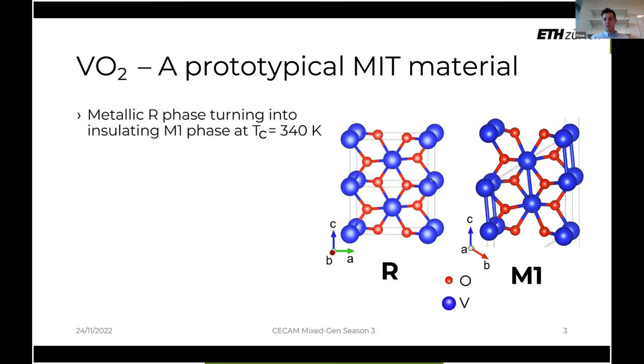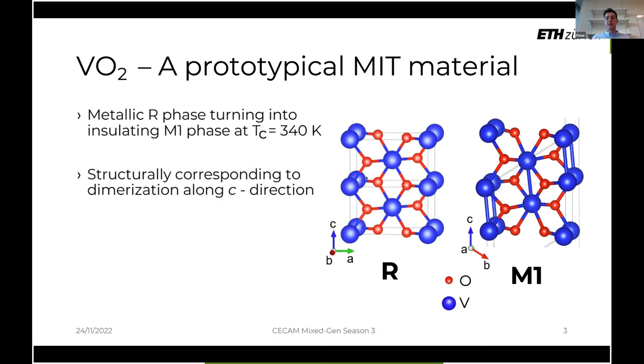The main structural difference between these two phases is the dimerization occurring along the C direction, as was very nicely outlined before. In the rutile phase, we have equidistant chains of vanadiums that are all in one line with the same distance in between. Whereas in the monoclinic phase, we now observe a structural dimerization with vanadiums getting closer together and tilting off axis.